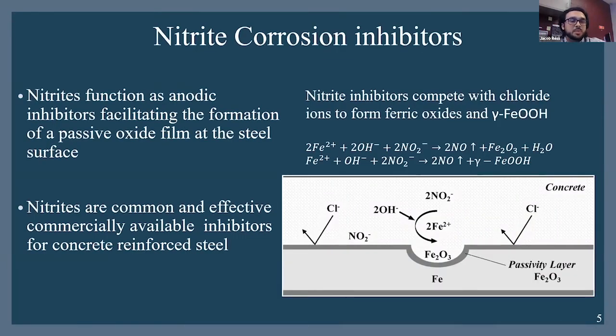Additionally, nitrite corrosion inhibitors are our inhibitors of choice, as they are one of the most well-known, the most widely used, and they are very effective. And what they do is they compete with the chlorides to form the passive Fe2O3 ferric oxide layers and oxyhydroxide layers on the surface that can protect against further corrosion.